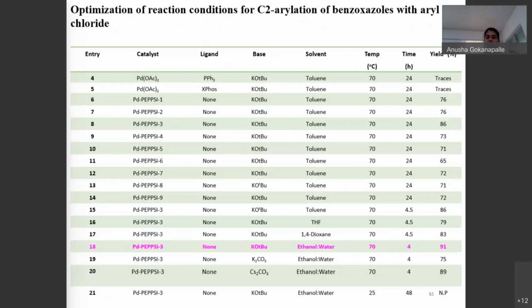Further, we have taken benzoxazole and aryl chloride as a model reaction for optimization. First, we started the reaction with palladium acetate and a ligand. We got a trace amount of product. Next, we investigated prepared palladium PEPPSI complexes for C2 arylation of benzoxazole with aryl chloride. Among all these, palladium PEPPSI 3 gave the best results because it has bulky, electron donating triisopropyl group, and palladium PEPPSI 6 gave the lower yields when compared to other palladium PEPPSI complexes because it has an electron withdrawing nitro group.